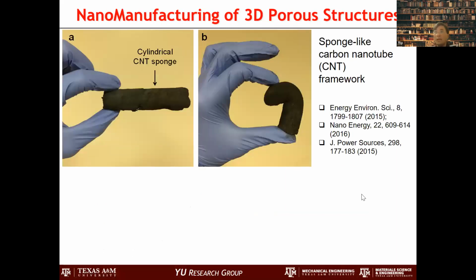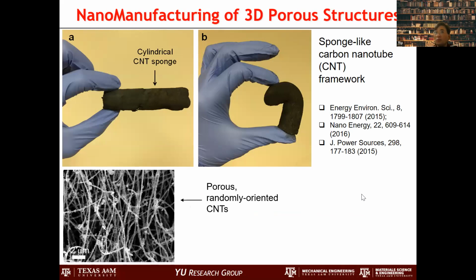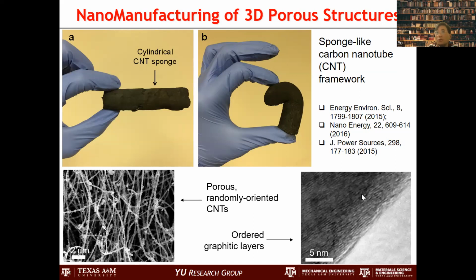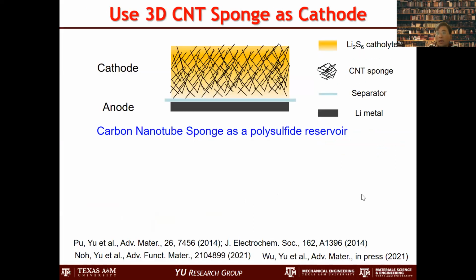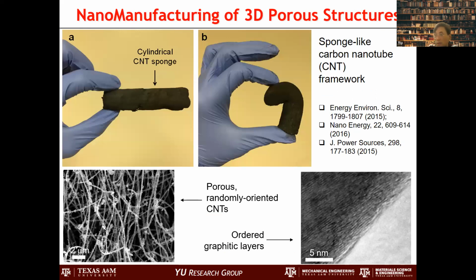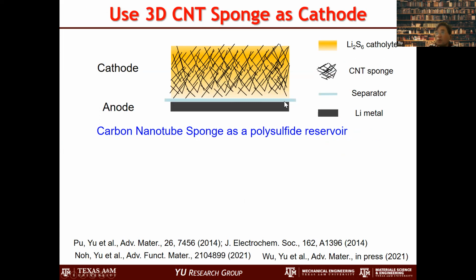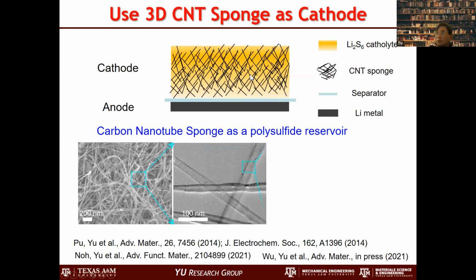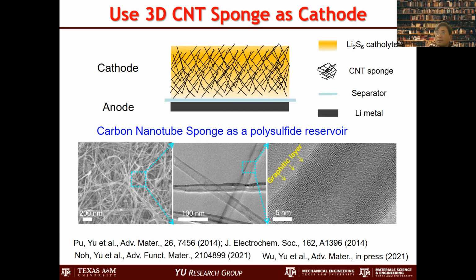So this is our carbon nanotube here, and it is freestanding and quite elastic. We can bend it this way without too much trouble, so we don't need any binder here. We use this porous, very elastic media, and no binder is required. So we made a cathode, and the anode is lithium metal, and we embed the polysulfide in it, like that. Then we made a battery and we cycled it.